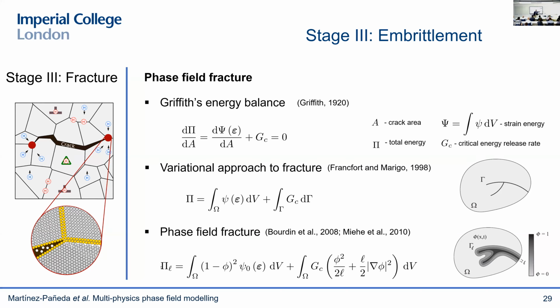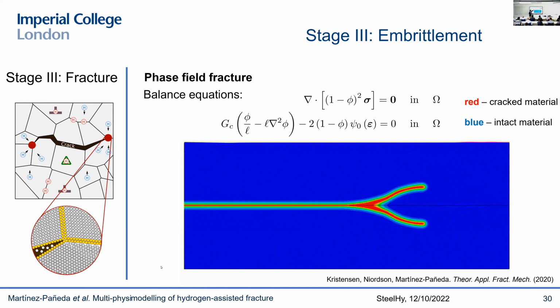So this surface integral becomes a volume integral, and then you use the phase field as a marker. It's kind of like a damage variable, right? It goes from 0 in intact material points to 1 in fully cracked material points. And then it's kind of a non-local damage model. As you can see, we have gradients, so we have a length scale, and then it degrades the stiffness of the solid. You can get a good overview here by looking at the strong form of the equation. So the phase field will reduce the load carrying capacity. And here, this is a phase field evolution equation, where it's essentially a competition between the energy stored in the solid and the fracture energy and toughness, something that we can measure in the lab.